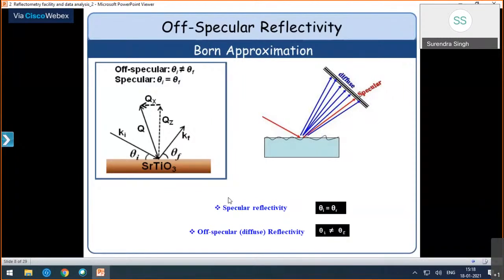And if you do this off-specular reflectivity in addition to your specular reflectivity, you get film interfaces - morphology, depth dependent structure. Though I said we don't know it from XRD, the layer structure we know, and the parameters which I have already mentioned, we get from this. So typically I have shown here also, as I showed in the Friday lecture also.